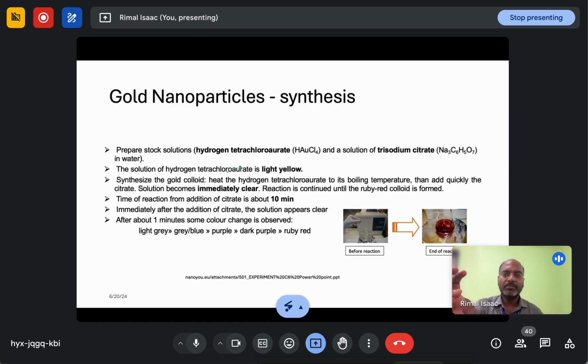You have to take chloroauric acid, or hydrogen tetrachloroaurate, and mix it with trisodium citrate. The quantity is very essential to make particles of a particular size. The color of the gold salt solution will be yellow. When you add trisodium citrate, it will immediately change to some color, let it be red. For example, if we know the correct quantity and add it, we prepare a 5 nanometer sized solution, and this color will be red.